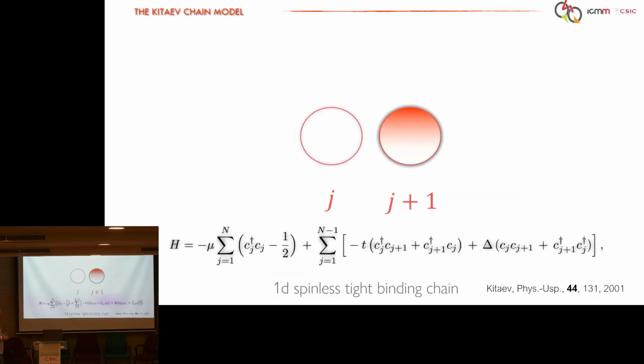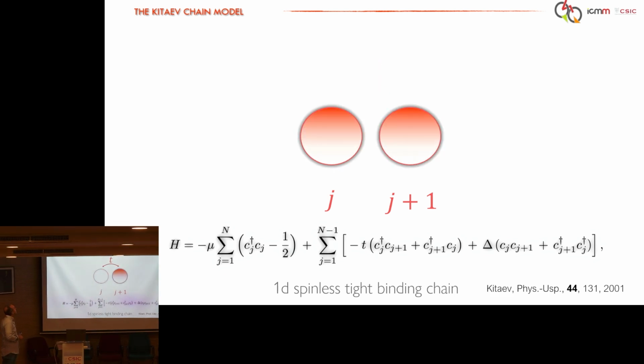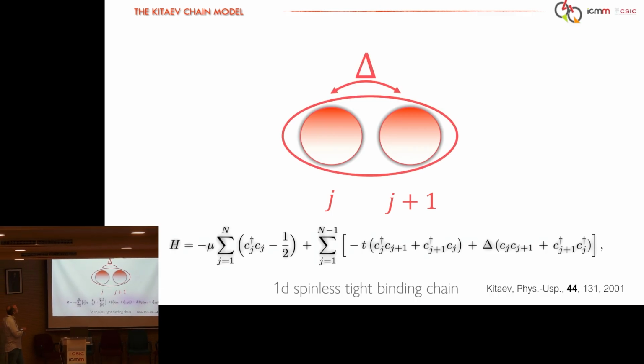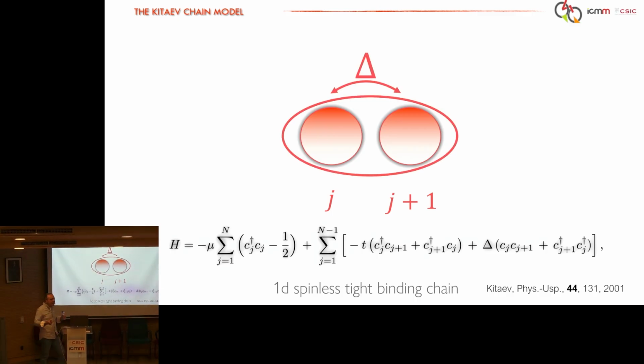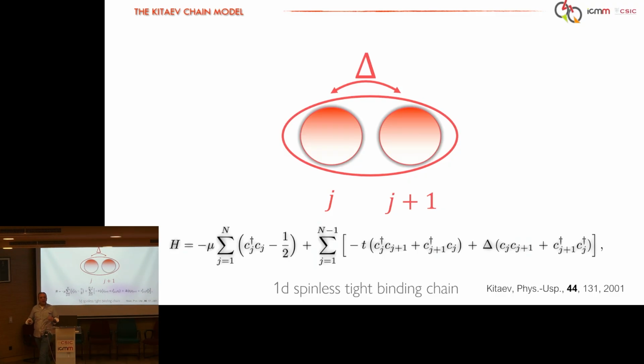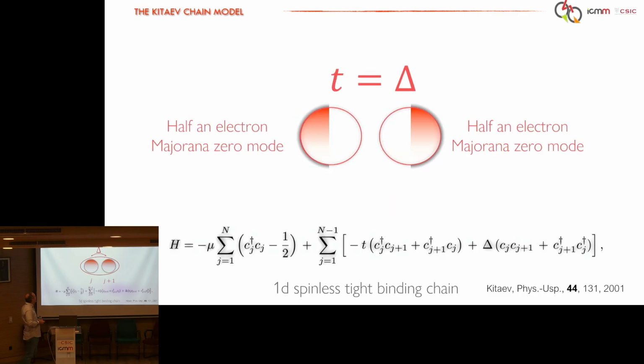The most basic model is what we call a Kitaev-type chain, which I'm not going to explain, but essentially the idea is that you have a chain, spinless, without any spin. You can have electron hopping between the sites, this is T, or you can have superconducting Cooper pair-like pairing, but between sites. Instead of having Cooper pairs with different spins, what you have is pairing between neighboring sites with a delta. So this model predicts that when delta equals T, you have these half electrons, these Majorana zero modes, appearing at the end of the chain.